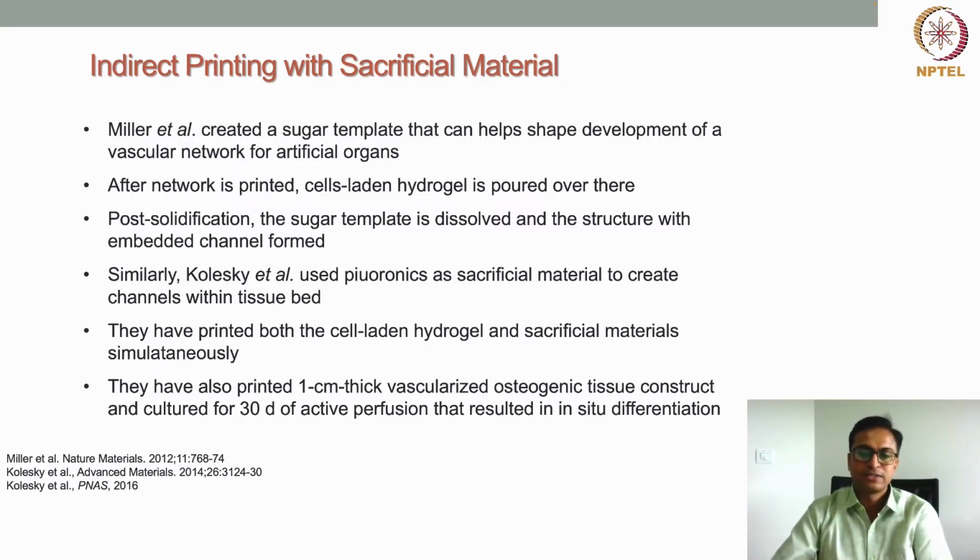And then they lowered the temperature to less than 20 degrees centigrade, where the Pluronic is liquefied, and then the Pluronic can be taken out easily by suctioning. So in this work they have shown that by using Pluronic as a sacrificial material, a cell-laden hydrogel with embedded channels can be created, and these channels they have further endothelialized by perfusing endothelial cells in a media through the channel. So the endothelial cells go and bind to the innermost layer, the inner lining of the channel, and then